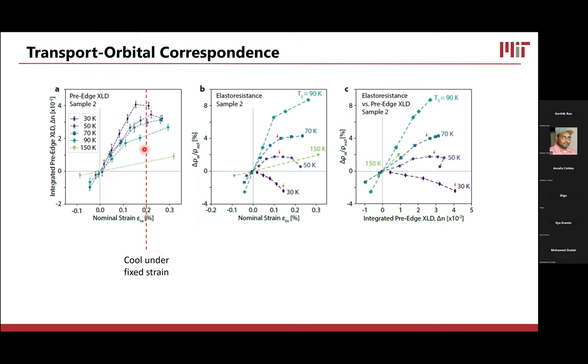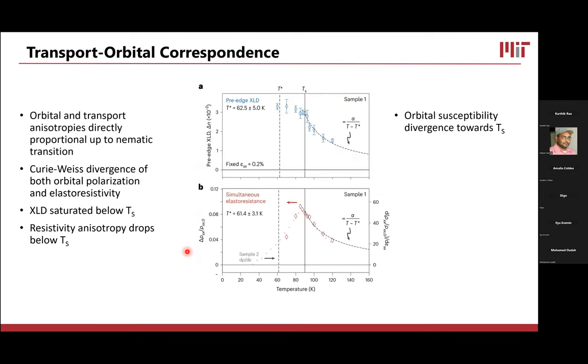If we go to a fixed amount of strain and we cool down under that fixed strain, then we get data that looks like this. So if we measure the XLD as a function of temperature under this large fixed strain, then we see an XLD signal that diverges towards the nematic transition. So this looks pretty cool. It's reminiscent of the diverging elastoresistivity or diverging spin fluctuations that we've seen in a lot of other works. And it's further evidence towards this idea of orbital driven nematicity.